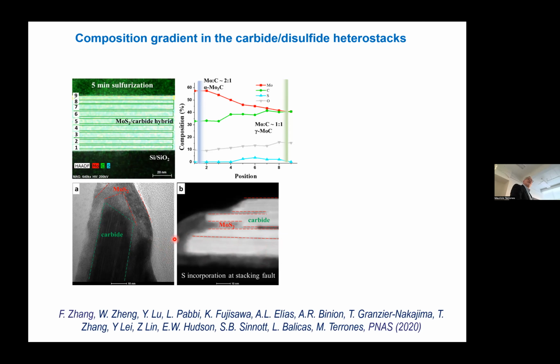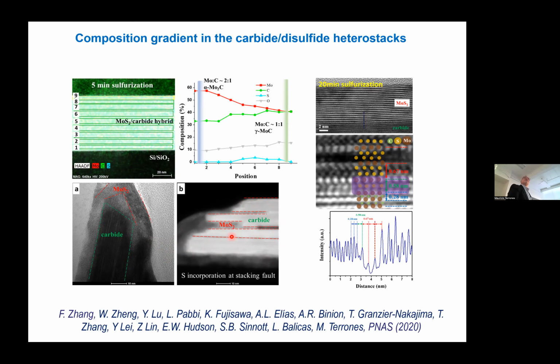I think it's traveling, or reacting, very fast along these stacking faults, and it happens from the edges, at different paces. It starts with one layer, but it goes all the way through because you have stacking faults. So that's what we think is happening with the mechanism.